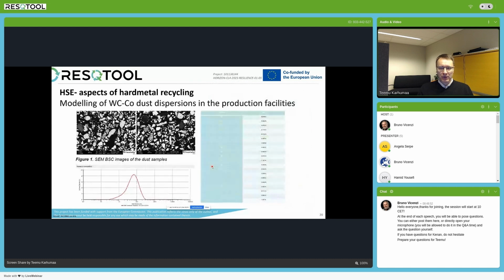And first of all, if we look at the modeling results, we took some samples from different locations in the production, and we were surprised how high the tungsten carbide content is in these dust samples. The composition corresponds very closely to the composition of our powder, and the particle size is also close to the particle size of our powder produced.